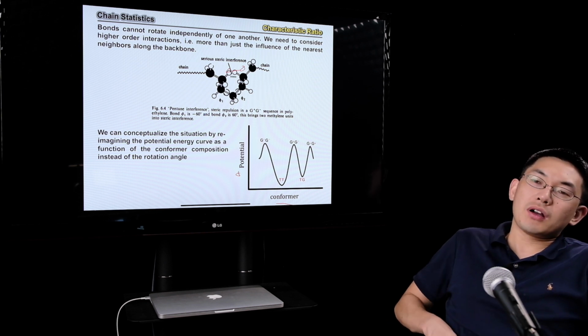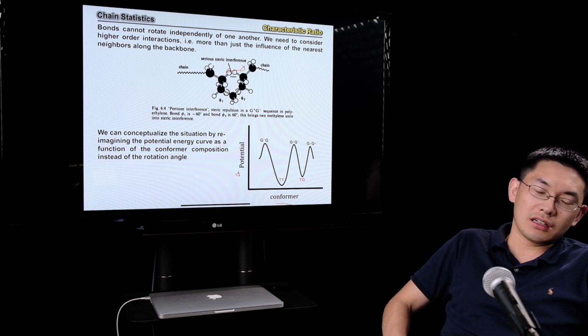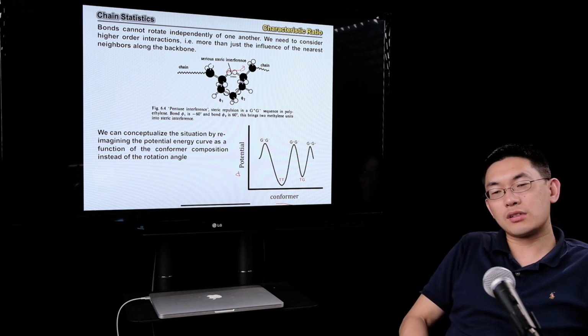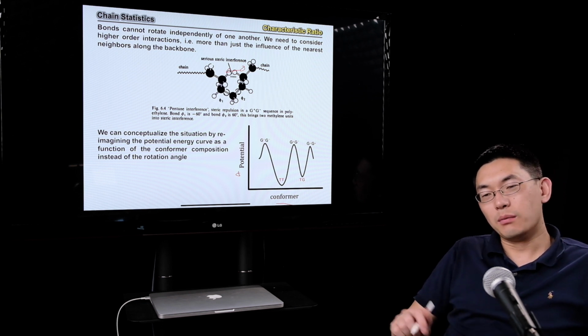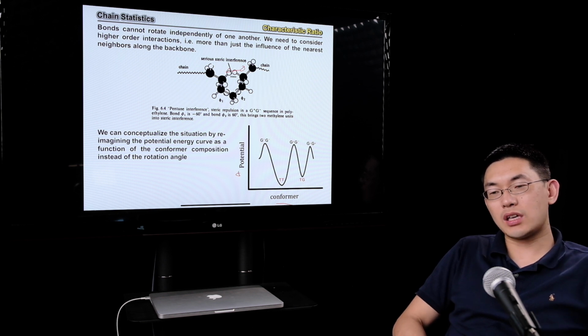The C infinity parameter can also be related to bond angle and rotation angle, so the rotation angle and dihedral angle. These two will be reflected in the calculation where you have 1 plus cosine theta and 1 minus cosine theta. I hope this will be helpful for you to understand the difference between those three models. I'm happy to answer questions in the live session. I'll see everyone later.